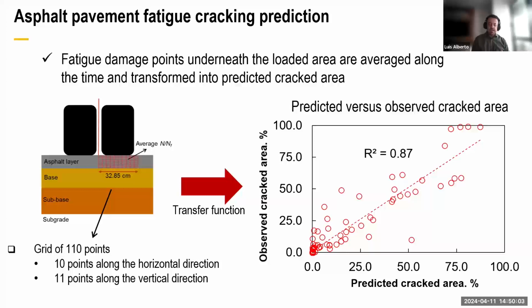Moreover, I used one example with a synthetic binder, and synthetic binders have a different rheology and different temperature sensitivity. Even though they have this different behavior, we could predict the material's performance nicely. Of course, we need to investigate the RAP usage in this protocol more, but the initial results using different materials, biomaterials, synthetic materials, and RAP are telling us that our current transfer function can handle these kinds of materials too. But we need to check better. It's a very nice question.